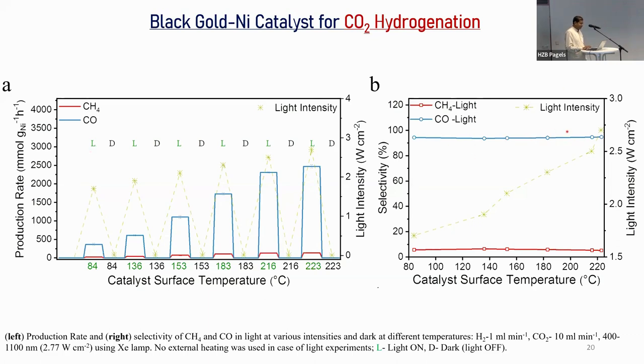Another interesting thing is, in terms of selectivity also, it's good. You have more than 95% selectivity towards CO and a very small amount of methane. It is a very strange result, by the way. Nickel generally gives you methane and not CO, but here it's giving you CO because the electric field plays a role in desorption of the reactant, right? The selectivity is all about how the intermediate desorbs from the surface. And here, because of this polarizing electric field, CO is somehow desorbing, rather than staying there and converting into methane.